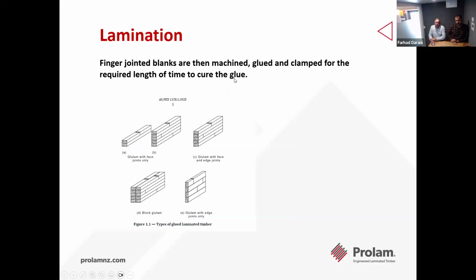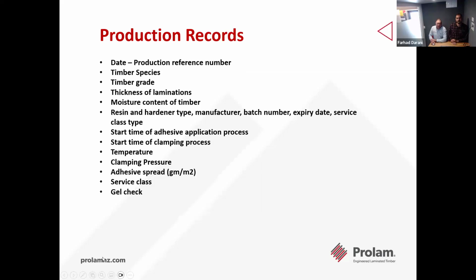Coming to lamination, so finger jointed blanks are then machined, glued and clamped for the required length of time to cure the glue. These are just a few examples of different ways we can laminate. And then our production records for the lamination process are fairly similar to finger joining. We're taking thickness of the laminations, the moisture content again, resin, the start time of adhesive application process, and the start time of clamping.